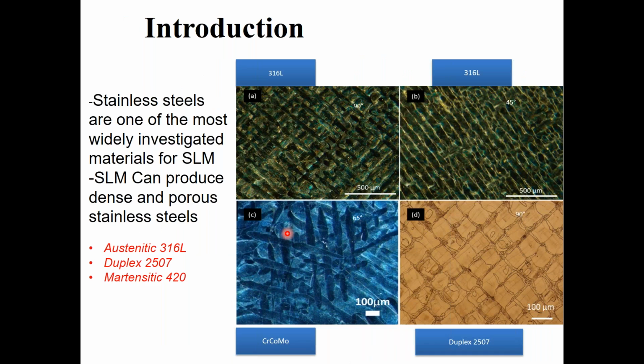So here are the 3 steels that we used selective laser melting to produce components: austenitic 316L, duplex 2507, and martensitic 420. And on the right side here, you can see the microstructure after the selective laser melting, and duplex stainless steels and chromium cobalt molybdenum alloy. How the microstructure looks like after SLM.